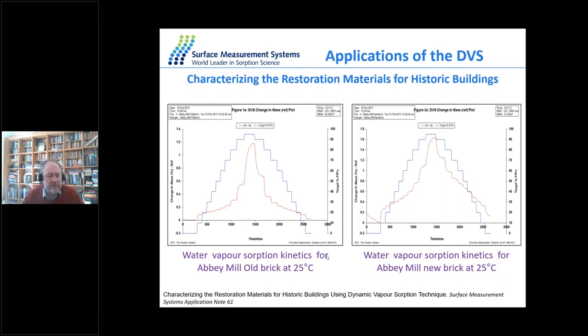So here is some of the original material. And I don't know what form it was. It might have been a brick powder, I'm not sure. But what you can see here is that this initial material took up about 1.2% water vapor. In other words, at 90% humidity, the brick material in the original building took up about 1.2%. The new material that they were planning to use for this refurbishment actually took up more water. And you can see here, it takes up 1.6%. And that is, by brick standards, still a much higher uptake and something that you might need to be careful about when you're designing your materials.